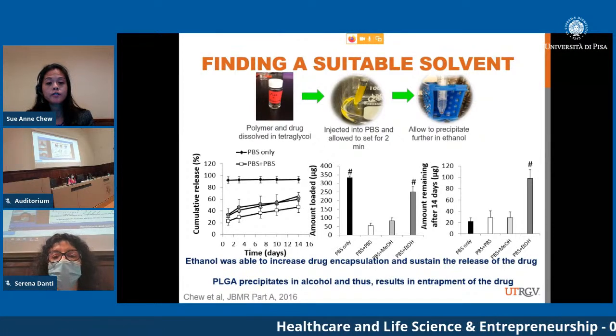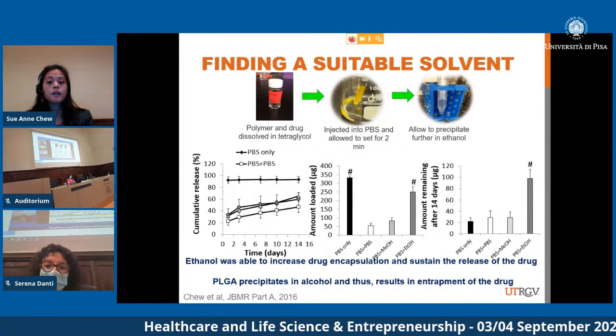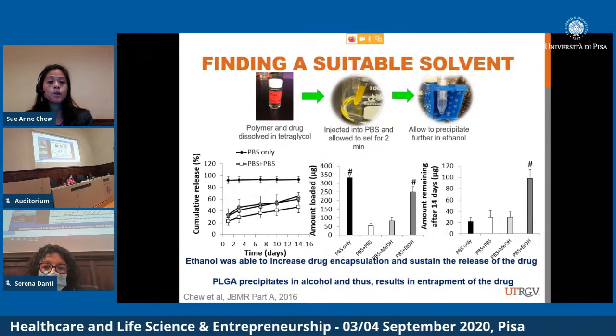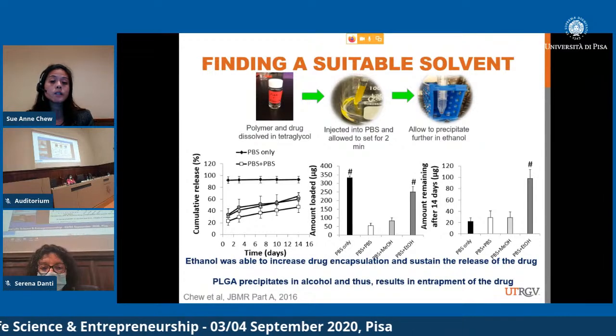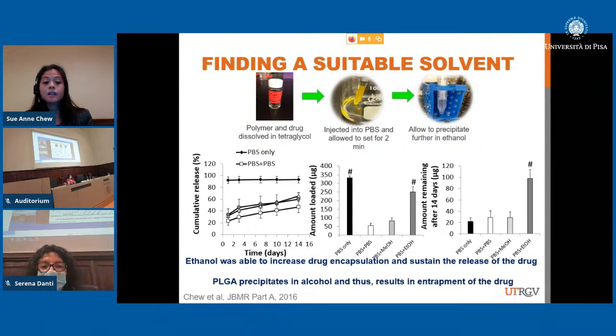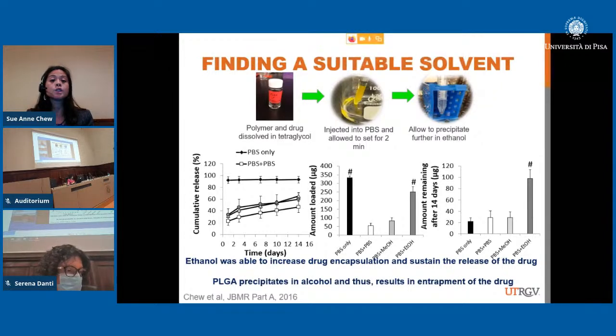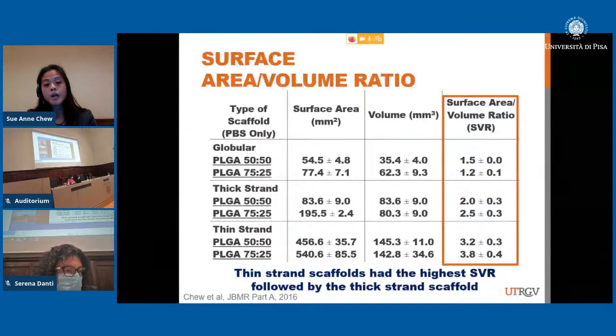And if you see in the graph, the one on the most right, we saw that when we used ethanol, we were able to increase the amount loaded and also sustain the release. And we believe this is so because the PLGA precipitates very well in alcohol. So, by going from a PBS solution to ethanol, we could further precipitate the polymer out of solution, trapping the drug inside.